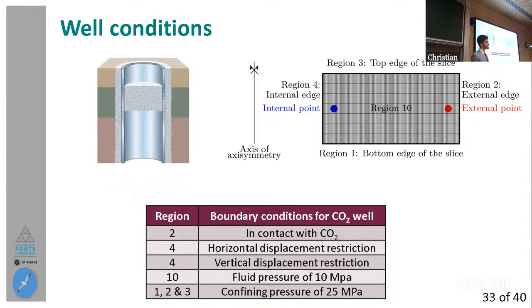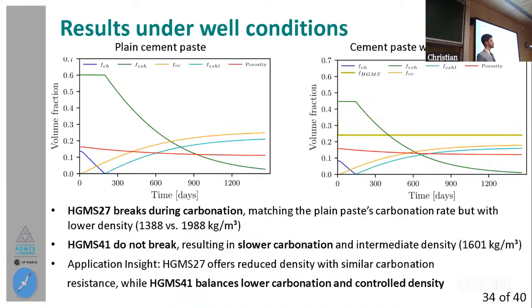The conditions applied correspond to a slice of the cement sheath located at 1,000 meters depth in the well, which are 10 megapascals of fluid pressure, and then a confining pressure applied in regions 1, 2, and 3 of 25 megapascals, and then a concentration of CO2 in region 2 at the external edge. So with this, I'm only going to show you some results on the variations in the volumetric fractions of each phase present in the cement with the spheres. Let's begin with plain cement paste, again, because it's the easiest.